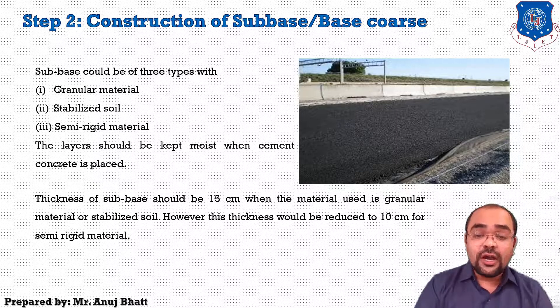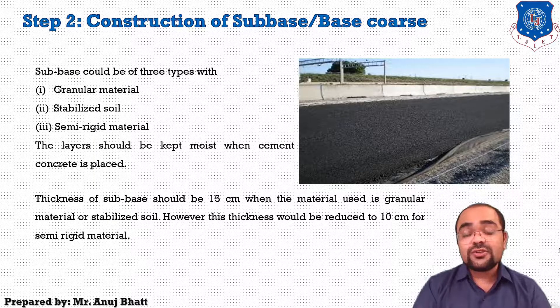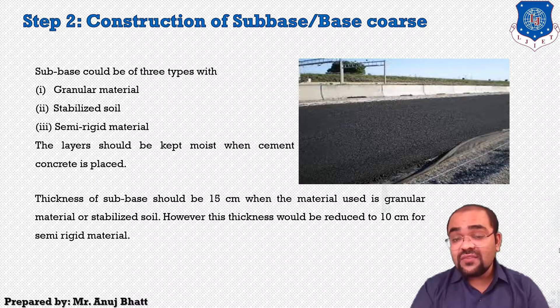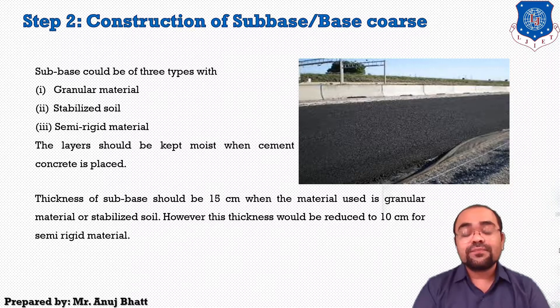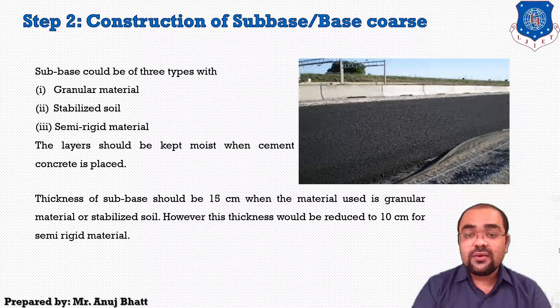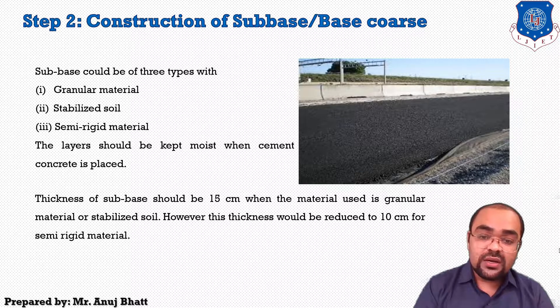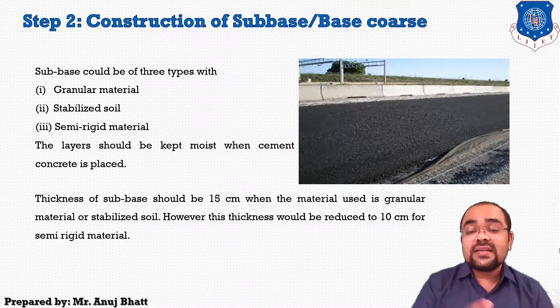If using semi-rigid materials, these include lime burnt clay, pozzolana concrete, lime fly ash concrete, lean cement concrete, roller compacted concrete, etc. The thickness of the subbase should be 15 cm when the material used is granular material or stabilized soil. However, this thickness is reduced to around 10 cm when using semi-rigid material.